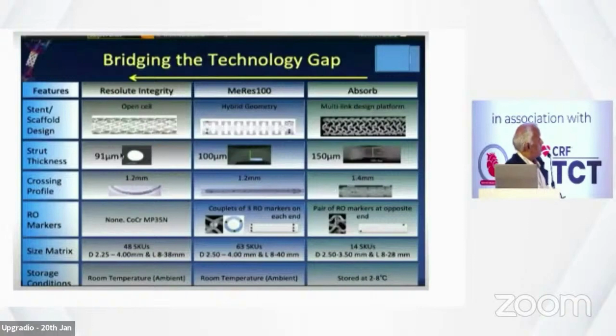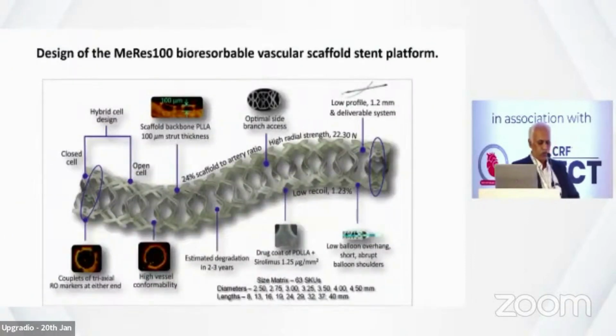Compared to the earlier scaffold, there is a change in the geometry, change in the strut thickness from 150 to 100. Crossing profile is decreased from 1.4 to 1.2 millimeters. More radio-opaque markers. Sometimes you have to struggle in the lab with BVS to position. And the size matrix is more. You can pick and choose many options. And storage conditions are more friendly. So this is the stent diagram. You can see it on the net. Same thing was what I mentioned. Central open cell, closed cells at the ends. Then all these high visibility markers, etc.